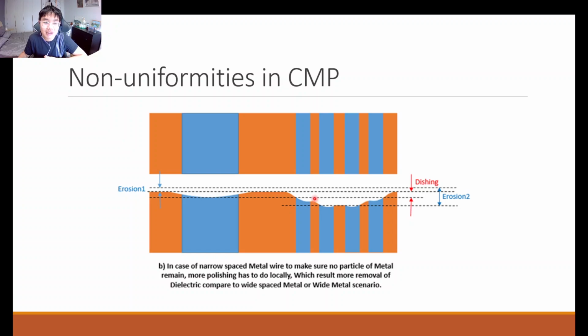More specifically, there are two kinds of non-uniformities. One is called dishing and one is called erosion. So dishing occurs here in the blue area, which is your metal area, especially if pad pressure is being applied in a way that's not suitable for the material, and in addition to unsuitable pad stiffness, it can result in your metal features having a downward curvature after planarization.